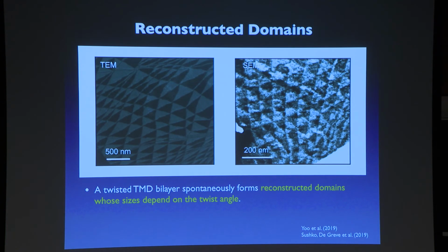So we can actually start to image them. And this, I will not get into details, but the thing is that you can do that using both transmission electron microscopy or scanning electron microscopy. Basically, using electron microscopy in a dark mode, in this particular case, in a particular diffraction spot, or a twisted angle, you can actually start to image all those restructurings at the nanoscale in those twisted bilayer samples, and then start to see whether they lead to observable optical consequences.